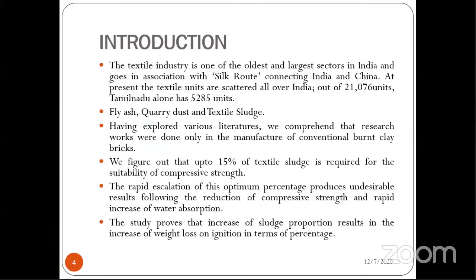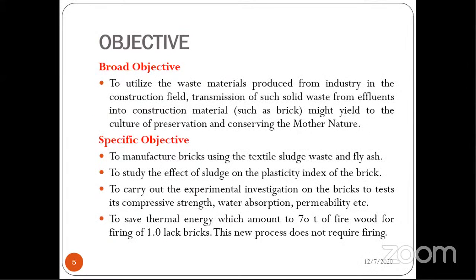Having explored various literature, we noted the research works were done only on the manufacture of conventional burnt clay bricks. So we figured out that up to 15% of textile sludge is required for suitable compressive strength. The study proves that an increase of sludge proportion results in an increase of weight loss on ignition in terms of percentage. Let's come to the objective.